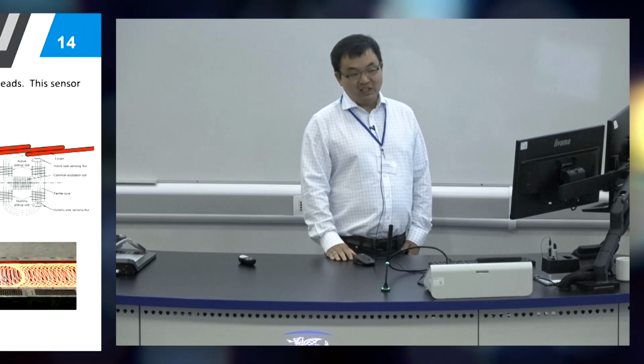The reason for doing that is, one, we want to start to get spatial resolution across the width of the sample. So not just wide strip, but we're starting to install the sensors at Liberty's narrow strip mill, where the strip can move to different positions, and the 4 sensor heads can decide which sensor head is actually testing the center of the strip and which sensor head's information we should read from. But even more complex than that, we are also installing sensors at the British Steel rod mill, where you have a rod laying out on a round table like that, which is a really interesting geometry.